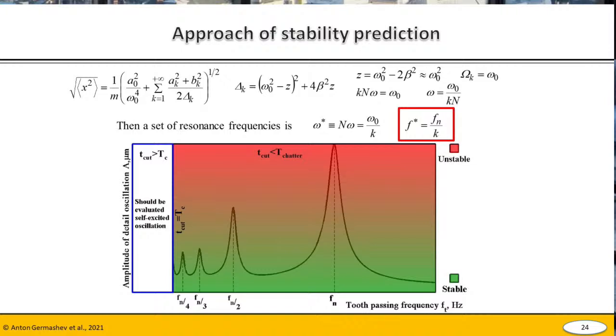So basically, it's a polar resonance, which is well known, and it's also a well-known fact that the spectrum of the milling process, of the high-speed milling process of thin-walled components, consists of an infinite number of high harmonics. That's why the resolving of our analytical approach shows that we have some peaks where the quality of the machining reduces significantly. And the next slide, please.